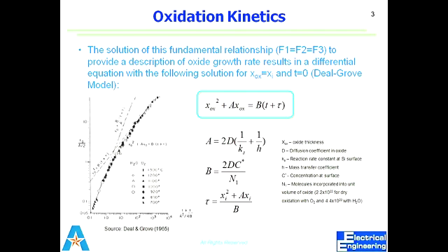In this case, when we have put the wafer inside the furnace maybe for 10 hours, there would be a very thick oxide layer. In that case, I'll come up with X oxide square equal to BT. X oxide square is equal to BT. So this is called the parabolic growth. You can see it's a parabolic relation.